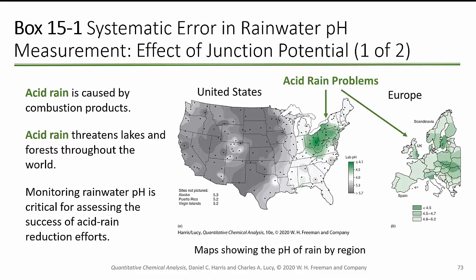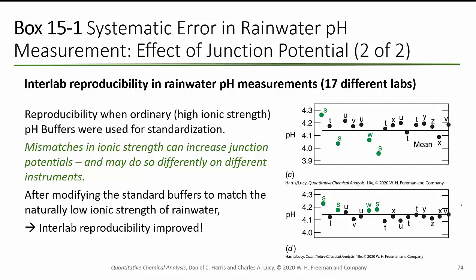Here's just a quick example of some of those systematic errors. We're looking at acid rain and what the pH is in different regions. So we've got some really low pH regions here, which are highlighted in green in both the US and in Europe. So reproducibility. When ordinary pH buffers were used for standardization, you ended up with some errors in there, and then they modified the standard buffers to match the low ionic strength of rainwater, and the inter-lab reproducibility improved. So they had a lot of variation up in here, right? And then they changed what their buffer system was. So that can actually be a problem with this idea of low ionic strength.